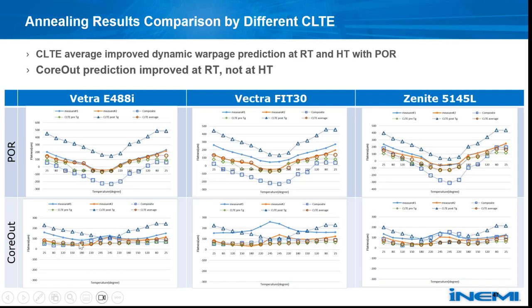So the effect of CLT calculation upstream on dynamic warpage is shown. The hollow triangle represents the prediction by CLT post-TG, and the orange circle is the result by CLT average. The absolute magnitude of dynamic warpage has shifted depending on the CLT upstream. Warpage magnitude predicted through both the CLT pre-TG and the CLT post-TG methods results in either an under-predict or over-predict scenario. CLT average improved dynamic warpage prediction at room temperature and high temperature with the POR design. And in the core design, the prediction improved at room temperature, but not in every case at high temperature.